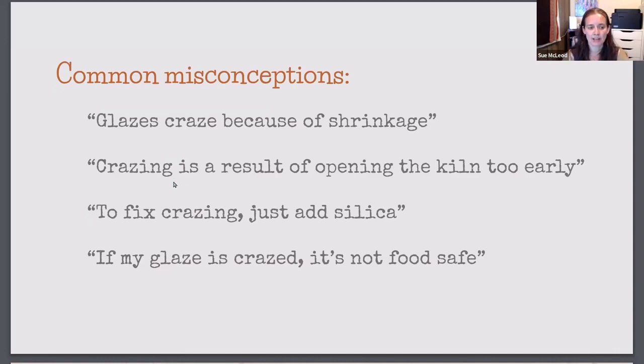Another misconception, crazing is a result of opening the kiln too early. If you open the kiln too early, the crazing will happen faster than if you let the kiln cool very slowly. But the crazing will still happen regardless of when you open the kiln. So it might happen right away. It might happen the next day. It might happen a month later.